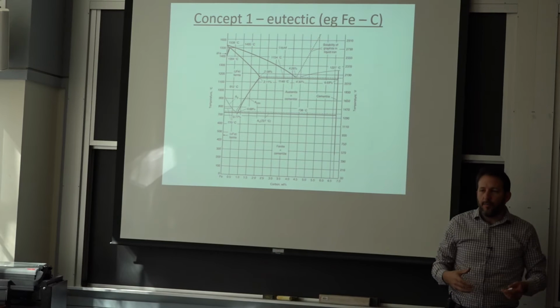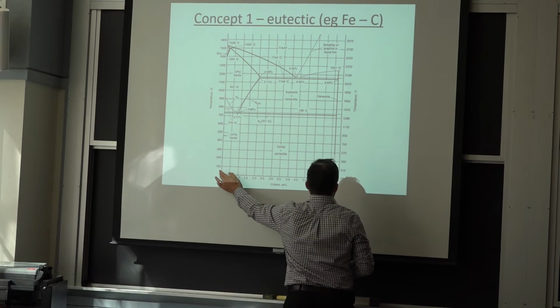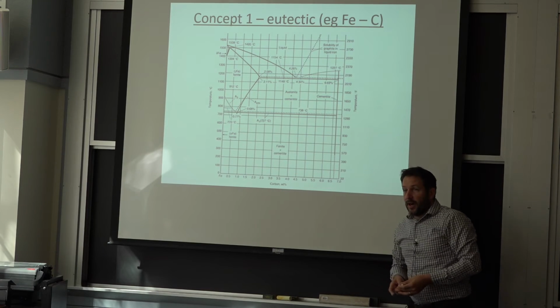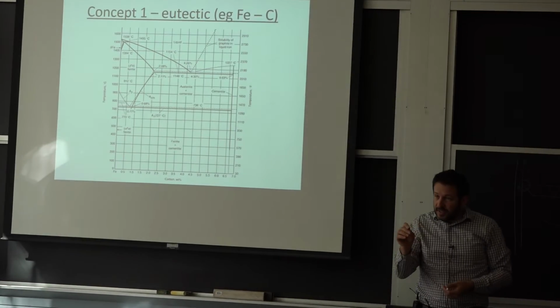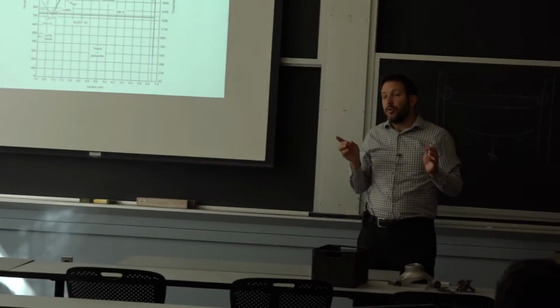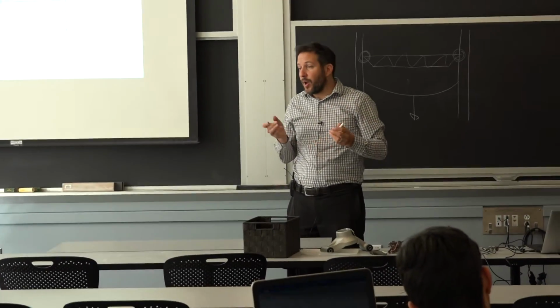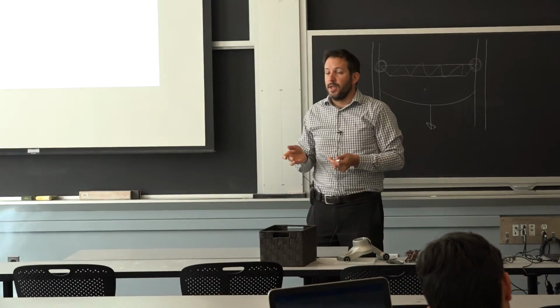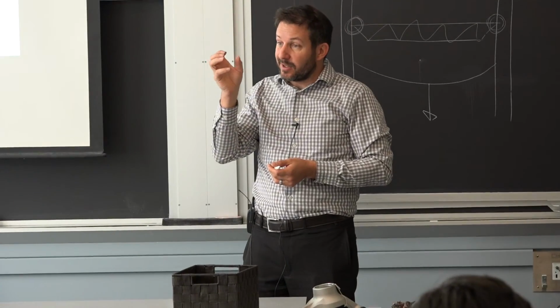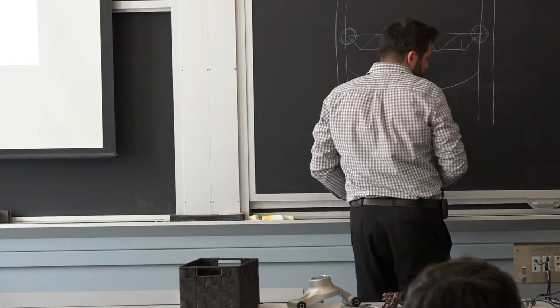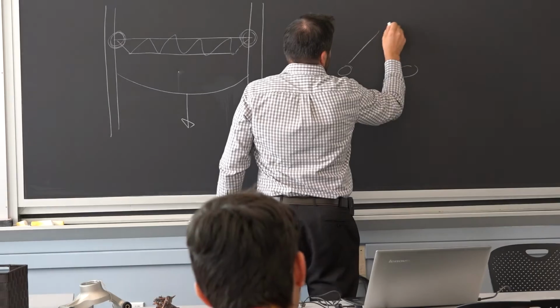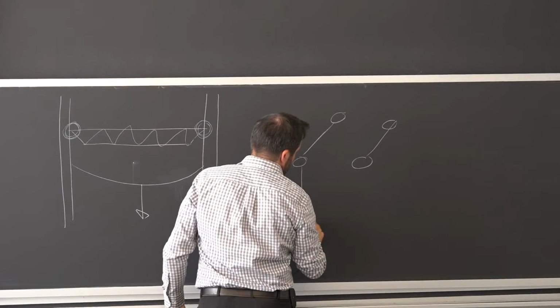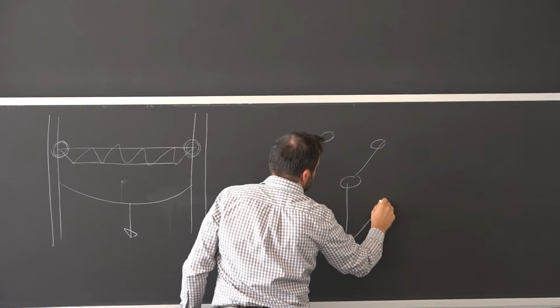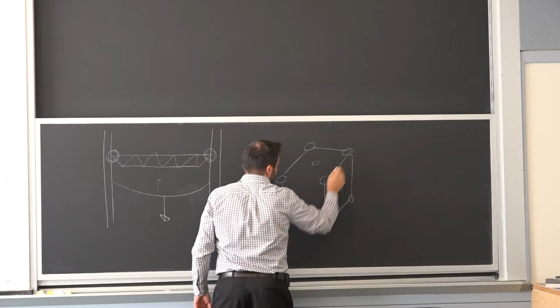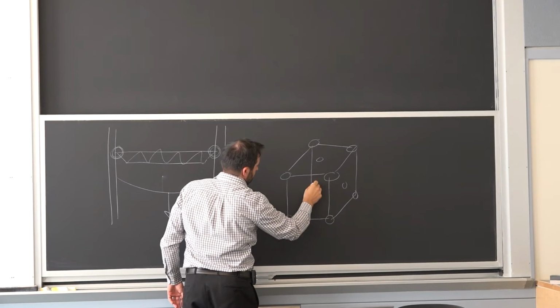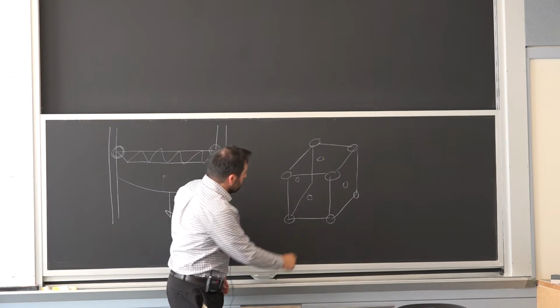If you quench, you avoid the decomposition into the iron and the carbon-rich phase. But there is a transformation in this particular case with steel. It is so unstable that it becomes a tetragonal structure. It goes from a cubic to a tetragonal as it's trying to accommodate that carbon in there. So if you start, and we didn't bring these, but you just start like this. It's a cube, face-centered cubic to begin with. So you have one here, you have one on top. You have one right here, one in the back, right there, and one at the bottom.